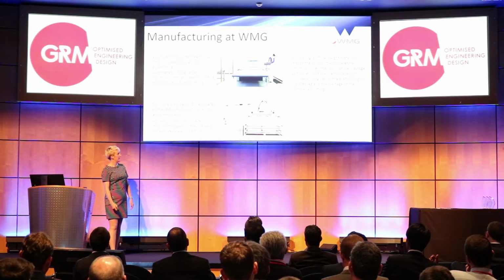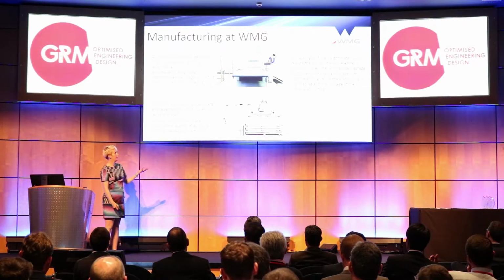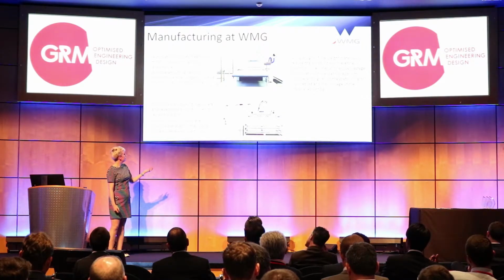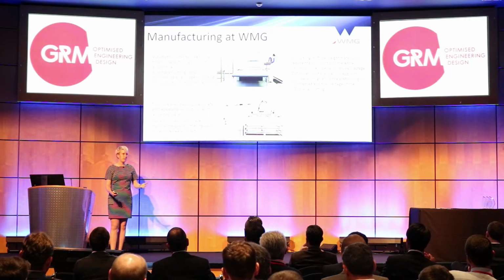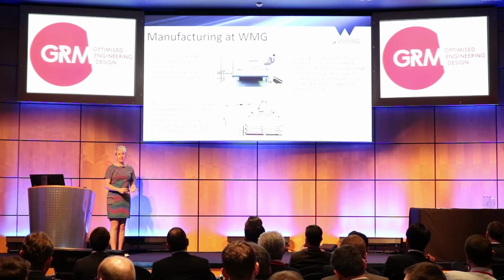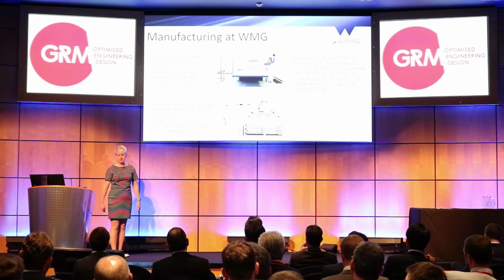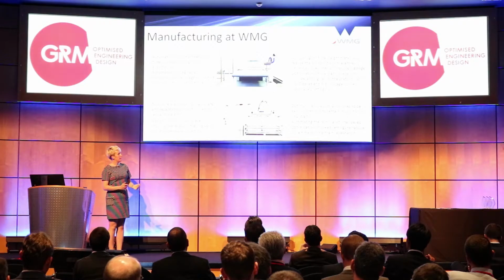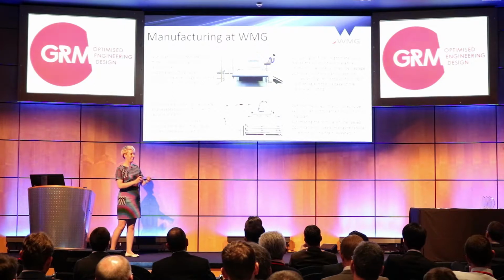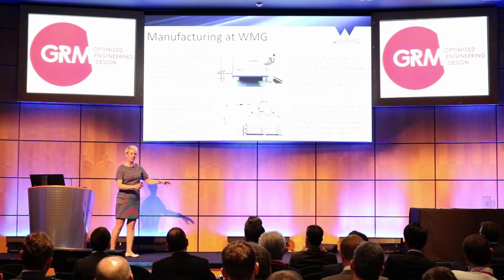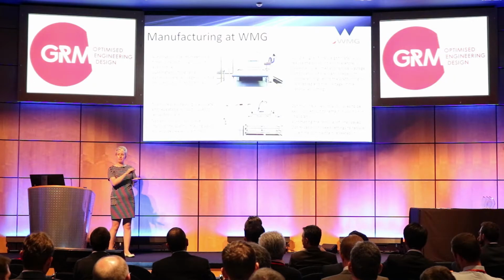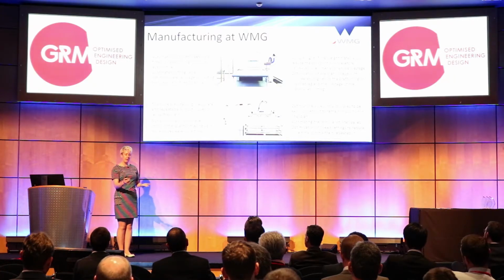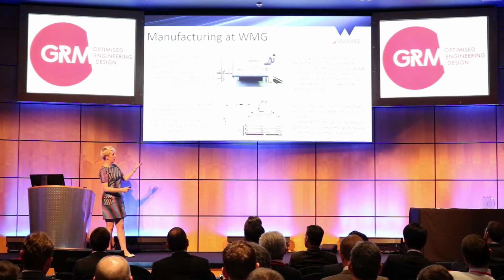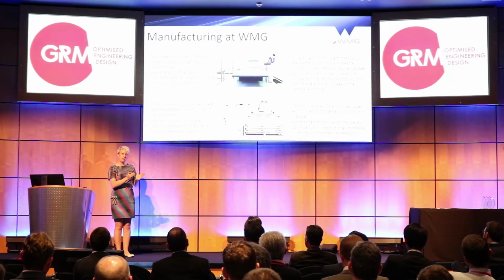So secondly is pick and place, so the layup of the materials. At WMG, we have the facility to do this by robotics. So the idea of using a robot, quite simple. Firstly, you decrease your time, and secondly, you make it a repeatable and accurate process. This was a challenge with the materials that we used because of the tackiness, so it was quite hard to pick them up but let them go exactly where you wanted to. And as well, they all have the backers on them. You've got to peel that off in the process. So we managed it, but not within the cycle time, I'd say, and that's areas of opportunity, and we have improved that on future projects.